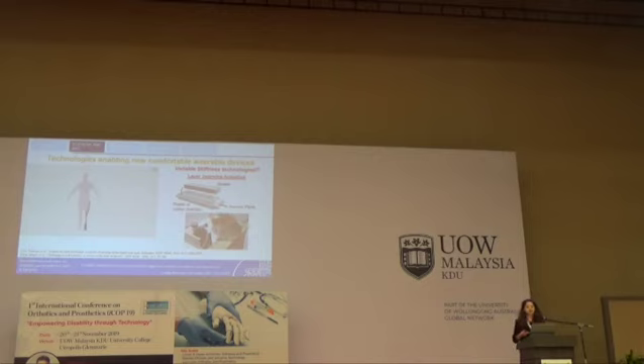A jamming system is based on several layers of low-cost materials, like, for example, sandpapers, contained in a sealed chamber made of flexible material like latex, silicone, or plastic sheets. In its resting state, a jamming system is highly compliant, so highly soft, while when you apply a vacuum pressure inside, the frictional interaction between the layers increases the bending stiffness of the whole system.